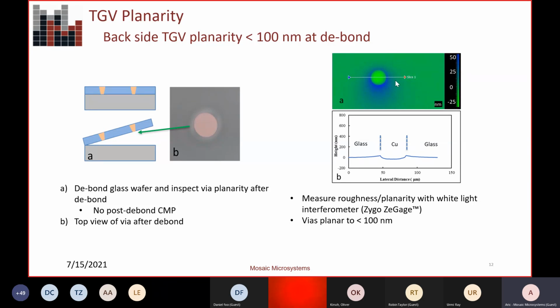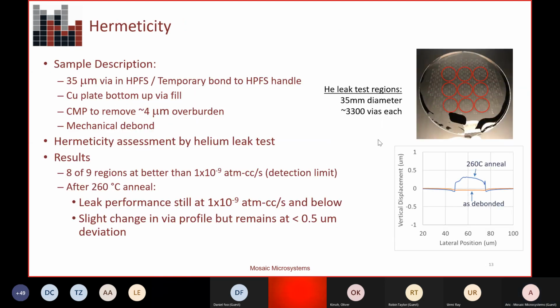And on the right, you see this is a Zygo white light interferometer, basically looking at the planarity of the copper and the glass surface. And without any polishing, you're better than 100 nanometers planarity on that back surface. So again, if you had a wet adhesive, that would wick up into the via and you would not get a good fill. But by having this very thin, very good interface, you get very nice planar and uniform via interface without any polishing.